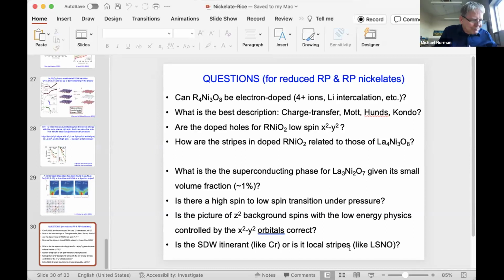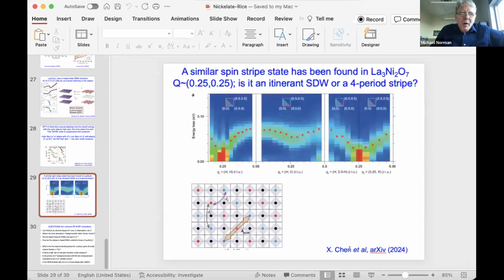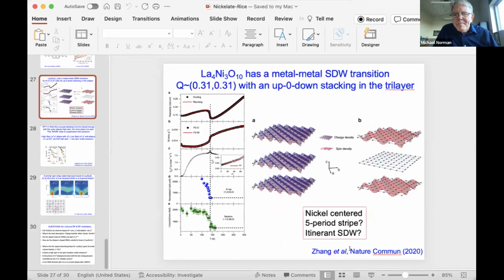Maybe I can follow up on that. It's not obvious to me that this order is purely magnetic. Right. So I forgot to mention this. If you look at the trilayer material, it's actually quite interesting. The interesting thing about the trilayer is that even though the outer layers are polarized and the inner layers are not polarized, if you look at the L dependence of the data, which is quite complicated, it looks like the CDW exists on all three planes. And in fact, the CDW and SDW have the same 2-to-1 wave vector ratio that you typically see in a stripe phase.